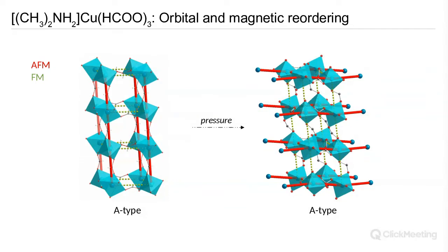We've called it a Jahn-Teller switch before. That's based upon the bond lengths. Presumably, the orbital configuration will follow. And if the orbital configuration follows, then presumably the magnetic structure follows via these GK rules that I discussed before. But I think this would be a particularly interesting case to explore then with charge density analysis again.